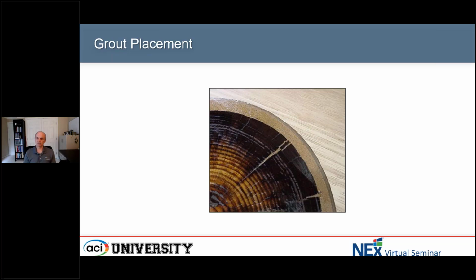And just want to emphasize the benefits of pressure injection is that you do get very good consolidation of the grout, right down to the point that you actually can start more or less injecting small fissures or cracks in the existing structure. So you can see the larger cracks in that timber pile, they've actually been filled with the grout as it was pressure injected into that pile. So with pressure injection, you do get very good consolidation and really, in some cases, very deep penetration of the grout into things like existing cracks and voids in that existing structure.